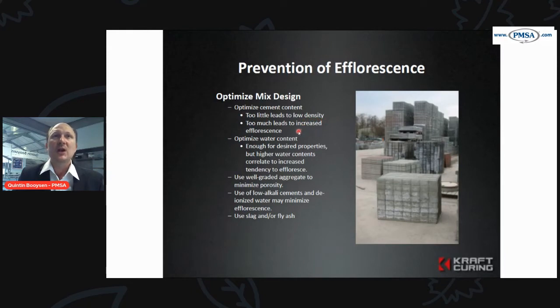Too much cement, in this case, ends up in, if you have a high cement percentage, which is often present in concrete roof tiles, where they may have as much as 20% or more cement, you end up with more free lime, that calcium hydroxide. So the higher your cement content, the higher the chance of efflorescence.